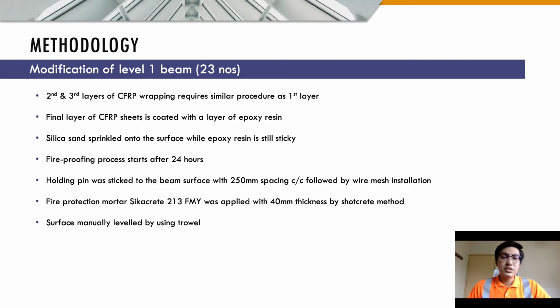Holding pins were stuck to the beam surface with 250 mm spacing center to center, followed by the wire mesh installation. Fire protection mortar Sikacrete 213 FMY was applied with 40 mm thickness by the shotcrete method. Finally, the beam surface was manually leveled using a trowel.